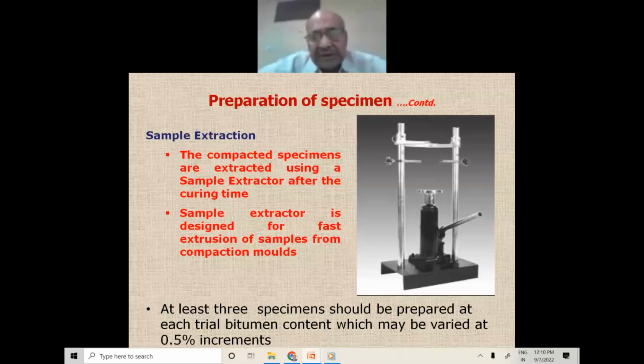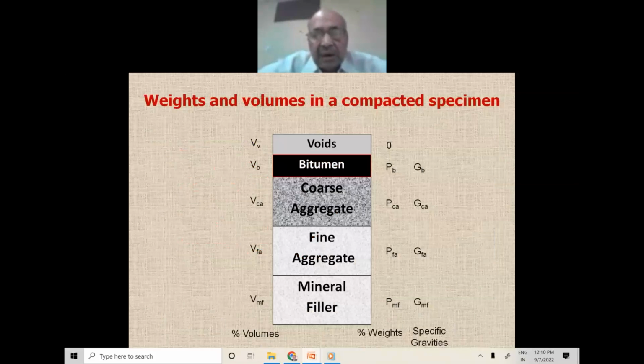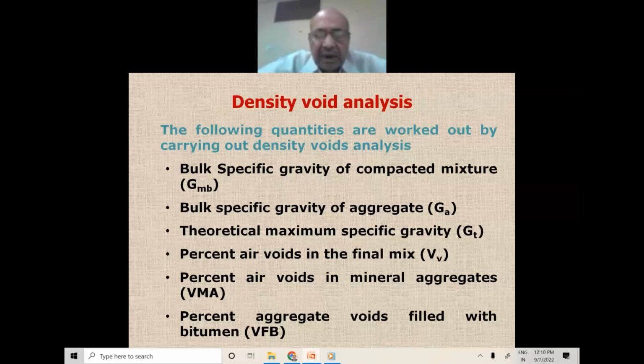Marshall molds for preparation of specimen of 101.6 mm diameter and 63.5 mm height are taken, consisting of base plate, forming mold and collar. Interchangeable base plate and collar are to be used on either end of the mold. The mix is placed in the mold and compacted by hammer with about 75 blows on each side. The weight of the hammer is 4.54 kg and height of the fall is 457 millimeter. Compacting temperature may be around 135. The compacted specimen should have a thickness of 63.5 plus minus 1.3 mm.